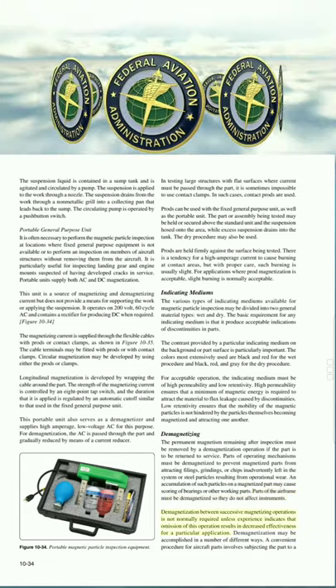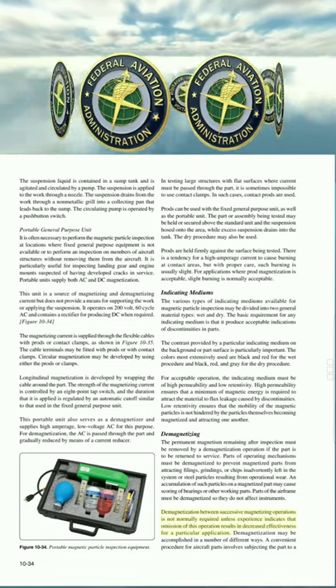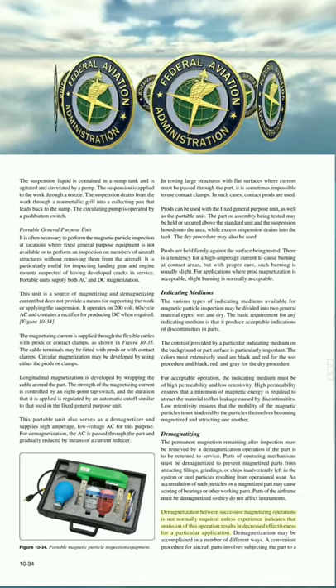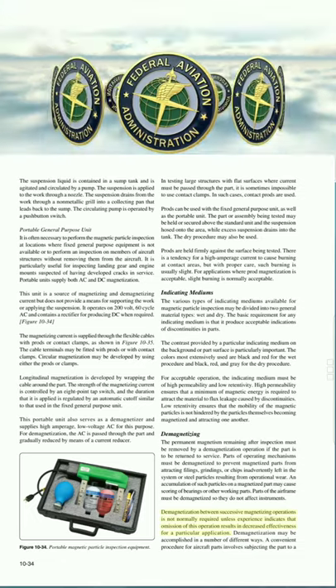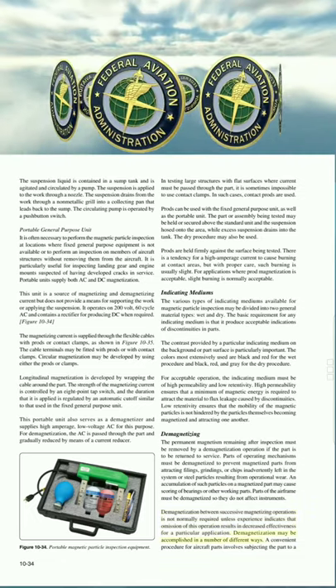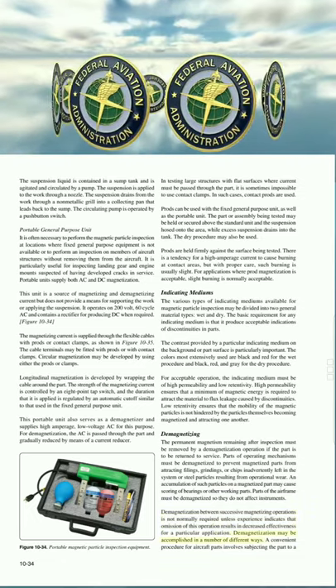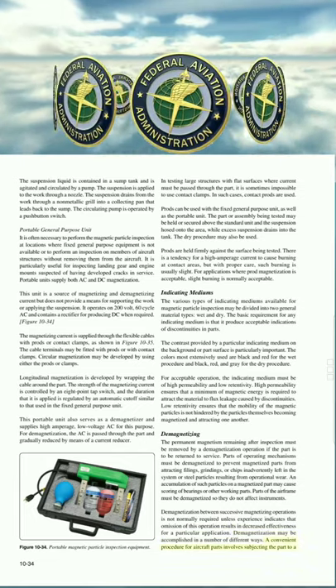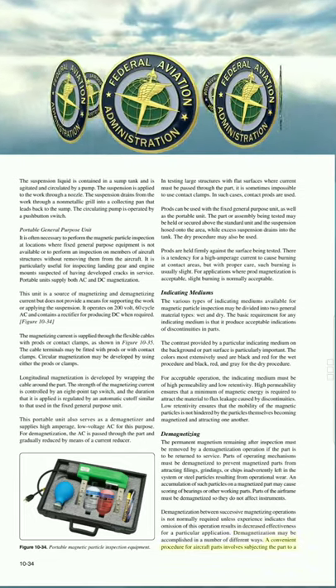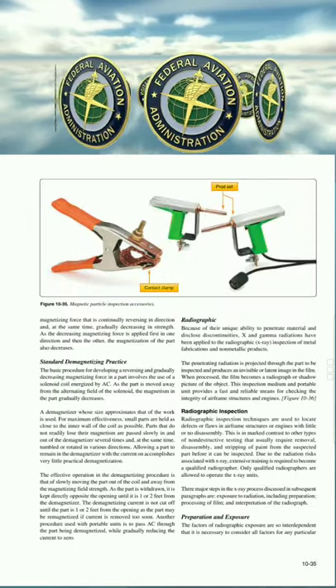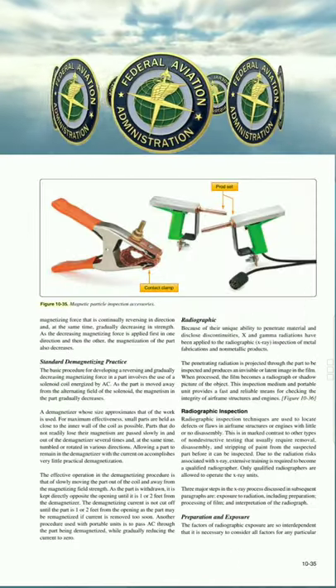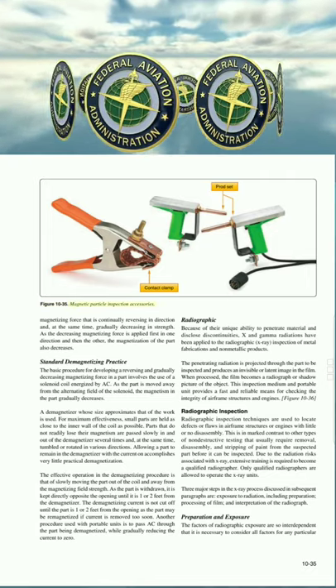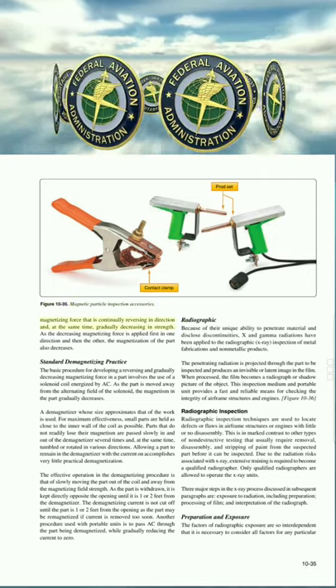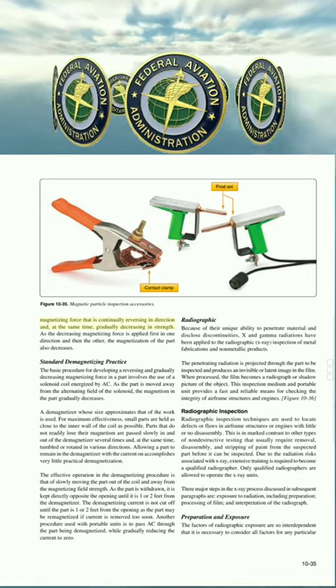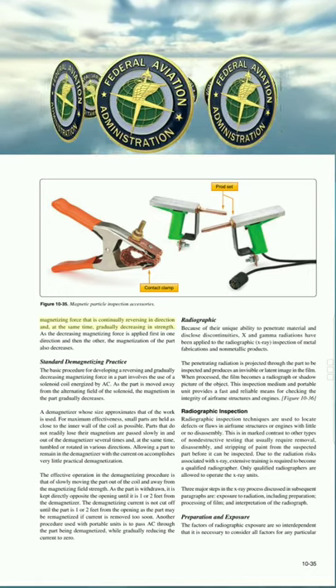Demagnetization between successive magnetizing operations is not normally required unless experience indicates that omission of this operation results in decreased effectiveness for a particular application. Demagnetization may be accomplished in a number of different ways. A convenient procedure for aircraft parts involves subjecting the part to a magnetizing force that is continually reversing in direction and, at the same time, gradually decreasing in strength. Figure 10-35, magnetic particle inspection accessories: prod set, contact clamp.